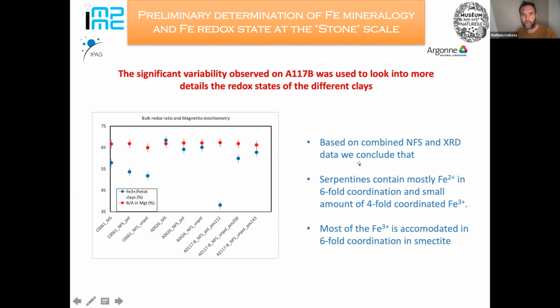And the other interesting result is that if you look at the isomer shift and the quadrupole splitting of this fit, you end up with the conclusion that iron 2+ is in 6-fold coordination, but iron 3+ in this serpentine is probably in 4-fold coordination, which is pretty unusual for clay minerals.